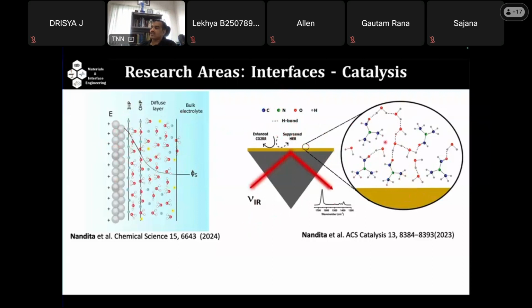If the bulk electrolyte structure hasn't changed much, but in the interface, electrolyte water structure means water coordination. In principle, one molecule of water can coordinate to four other molecules of water. Now it can actually have a hydrogen-bond-free system also, or three hydrogen bonds or two hydrogen bonds, etc. Depending upon that, by controlling the number of coordination, your actual energy to release the hydrogen from water also changes. So can you do such changes or not?